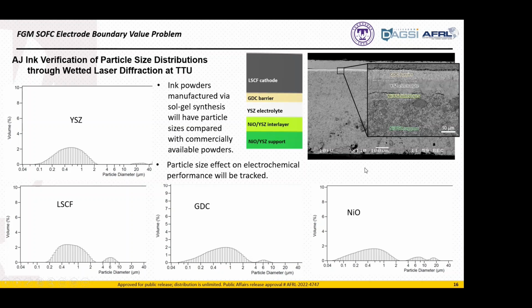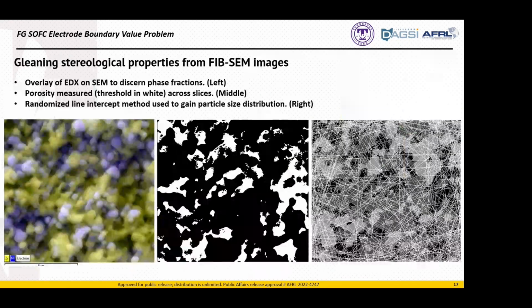Yeah, but there was one slide that you showed nickel and zirconia particle size, and you said nickel instead of nickel oxide. Oh, well, so there's going to be a difference between the sintered and reduced final microstructure, which is going to be primarily nickel. So the nickel oxide gets reduced. Yeah, but in fabrication, the starting point, you use nickel oxide. Yes. So I'm sorry if I didn't make that clear. We are trying to track correlations between the initial green body and then the final microstructure, but the simulation of that sintering process would be a whole other project unto itself.